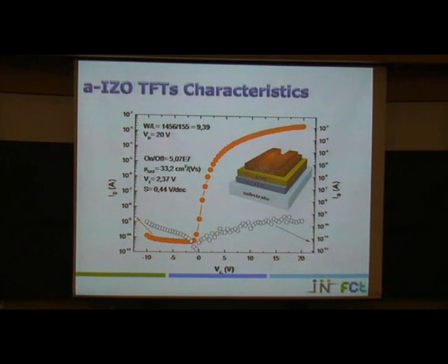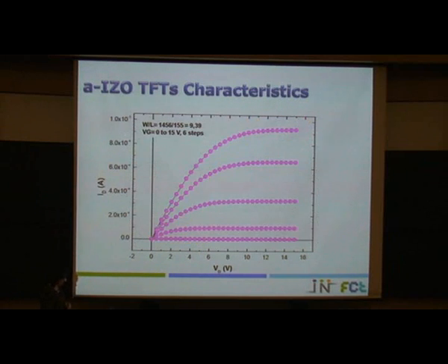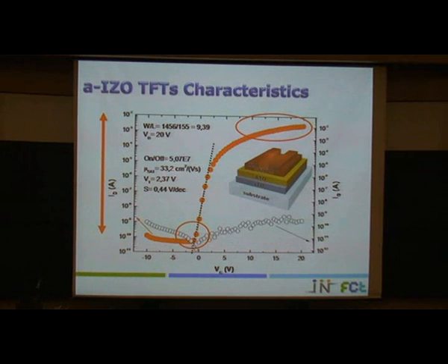In some cases we reach 10 to minus 12, 10 to minus 13. But of course this depends not only on the semiconductor that we are using, but on the dielectric layer and also the interface between the dielectric and the semiconductor. Because for a device this is a little more complicated, and of course the interfaces play a crucial role. Just for you to have an idea, the thickness of the semiconductor is around 10-20 nanometers, which is very, very low. I didn't mention, but for example, we obtain mobilities higher than 30.